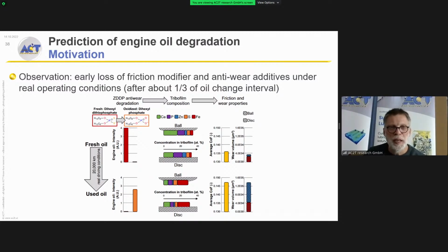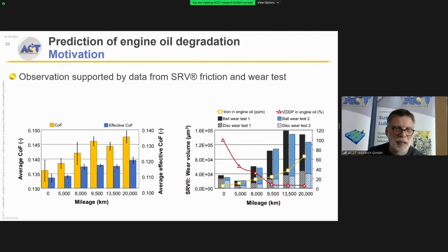One of the most prominent additives in such an engine oil is what is called ZDDP. This is an anti-wear additive which degrades by oxidation or partial oxidation and then loses its ability to prevent wear. You see that in the chemical composition, which we use here to identify the state of the oil. I will come to that in a moment. But you also see it when you take this oil and do some laboratory friction and wear tests: the friction force or coefficient of friction and also the wear rate will increase when the oil is almost at the end of its life. Here are just some example data from our in-house friction and wear tests. You can see that the coefficient of friction rises and also the wear volume or wear rate rises.